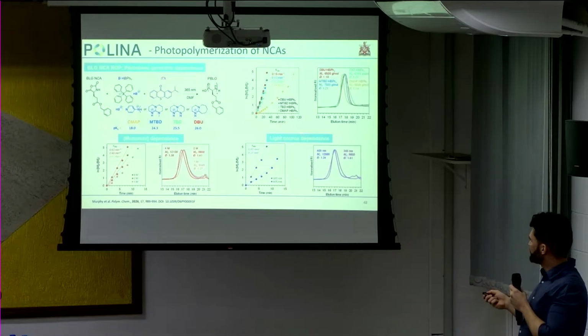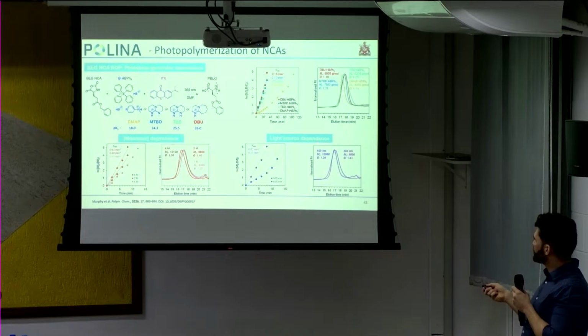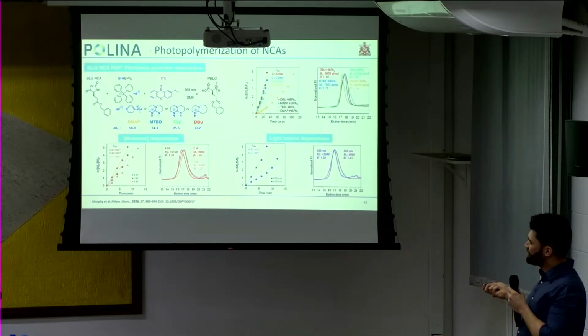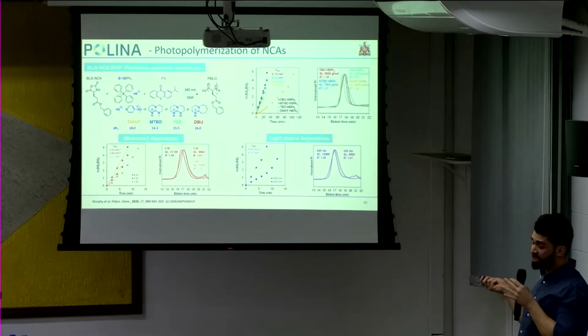Light source dependence: even though it could use blue light, 405 nanometers, the UV was more effective. The blue light provided higher molecular weight, but as we said, we actually preferred faster kinetics over molecular weight, because in the end we would have a network, so it wouldn't make that much difference for this first stage at least.